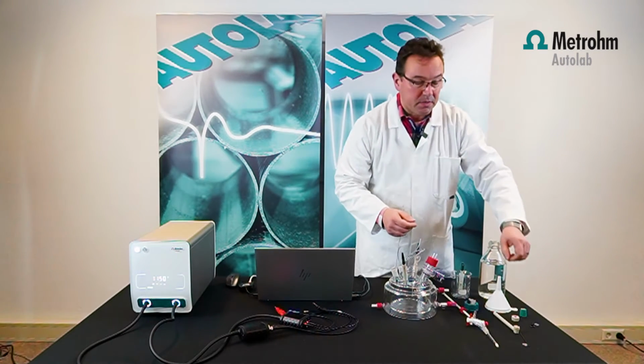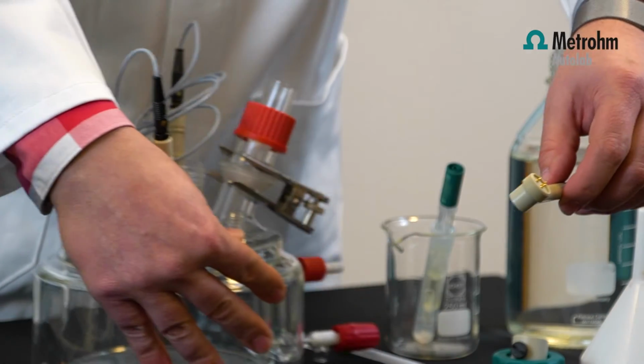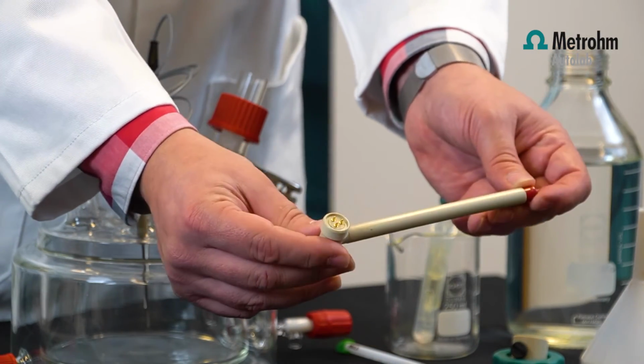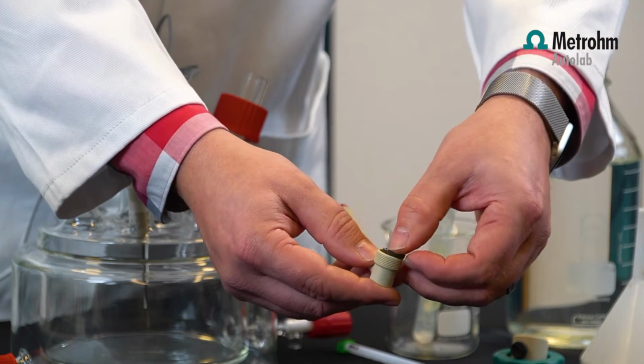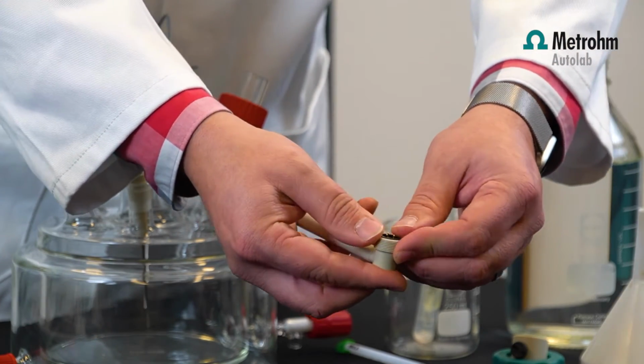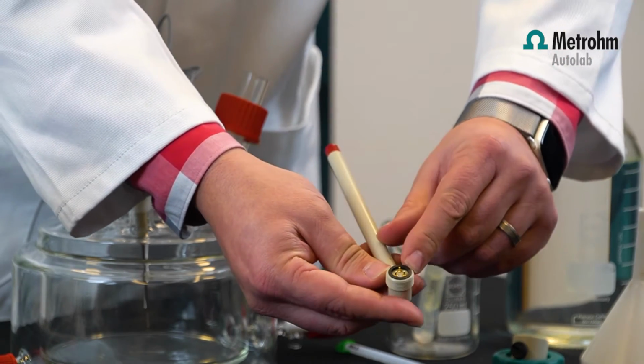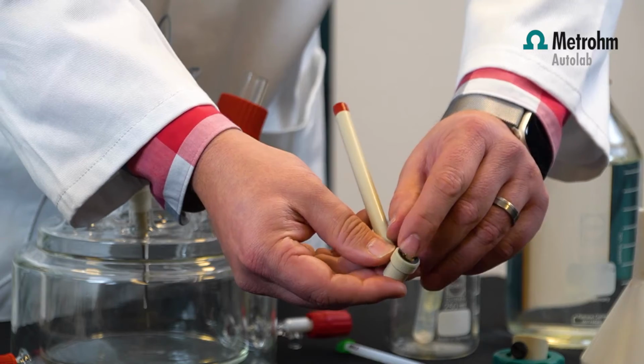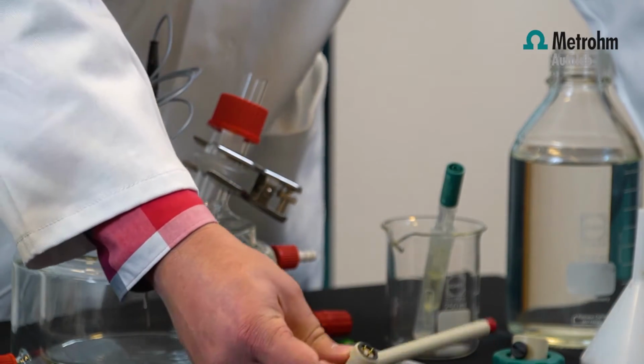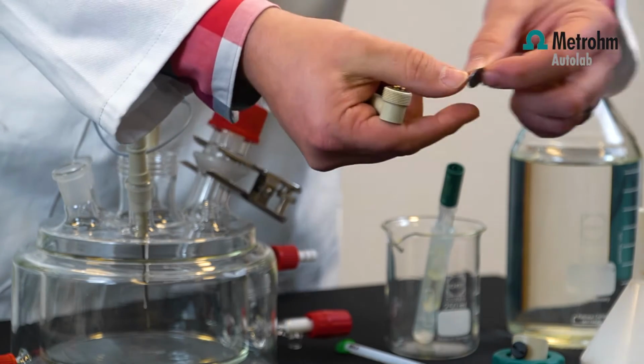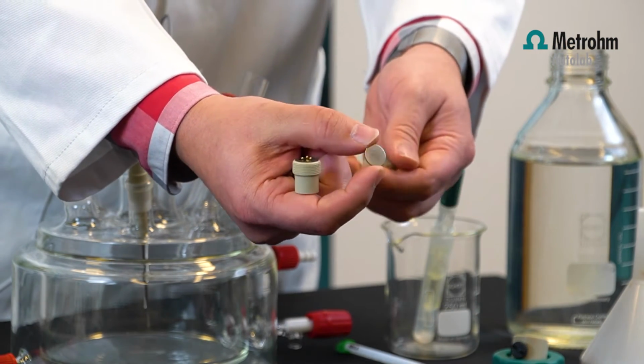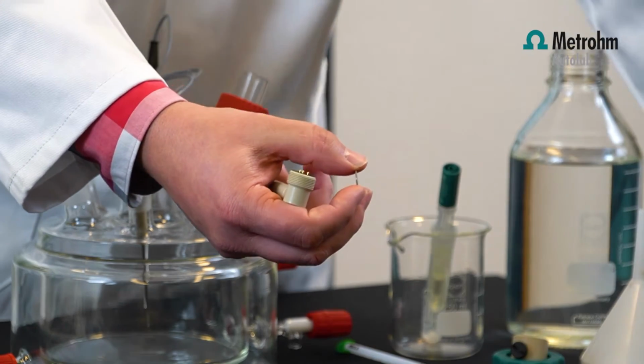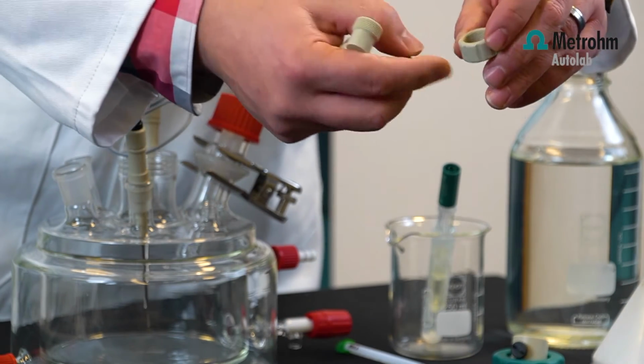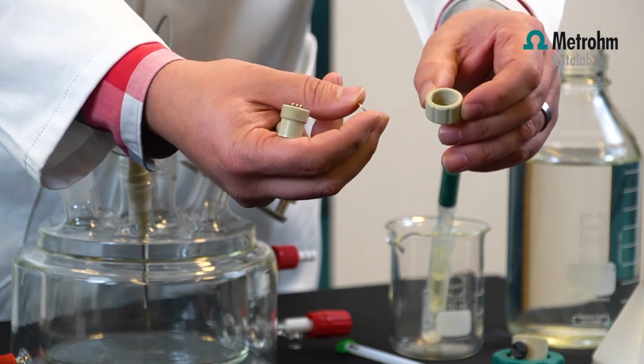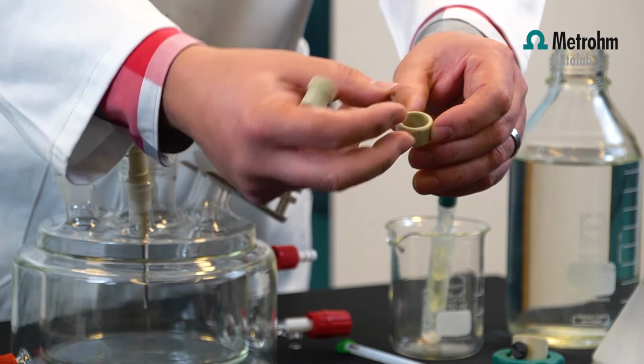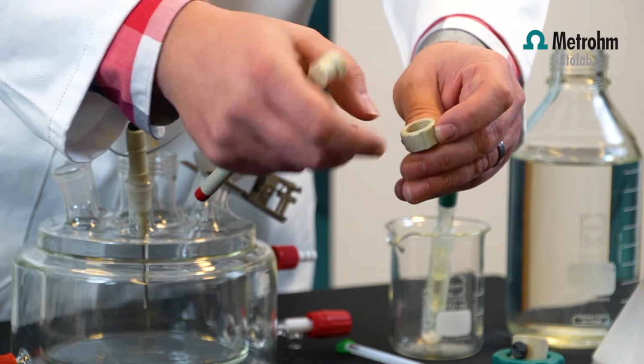The working electrode, this is a little bit in detail, so we focus more on the working electrode. So here we have the sample holder. First we put a rubber ring inside the sample holder. These are some pogo pins, which you can see, which you can press. And this makes contact with the sample, and the sample is a metal disc. This is just an example. You can put any type of metal or alloy in it. First, you put an O-ring in the holder. So here you press an O-ring in the cap, and then you put the sample in the cap of the sample holder.